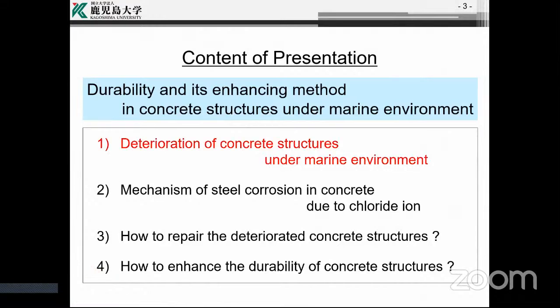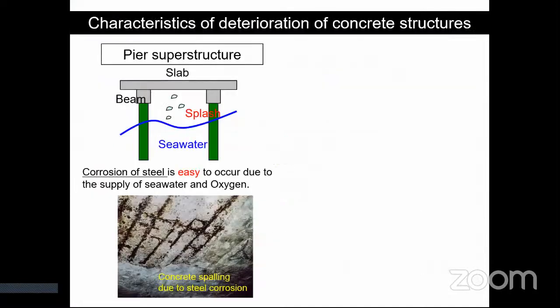Okay, I'll explain characteristics of deterioration of concrete structures in the marine environment. In a pier superstructure, steel corrosion due to chloride ion in seawater is a major cause of deterioration. Corrosion of steel easily occurs due to the supply of seawater and oxygen, like this.